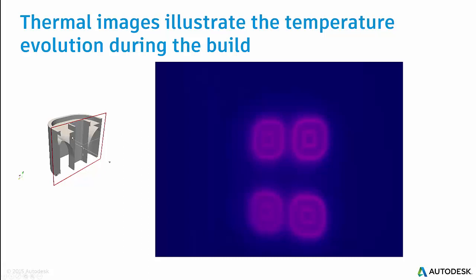Higher on these thick sections, we can have problems like oxidation or the material getting so hot that it burns away. We want to flag regions of the part that are likely to encounter those problems so that a user can modify the parameters before going to the machine and achieve a more uniform temperature distribution.